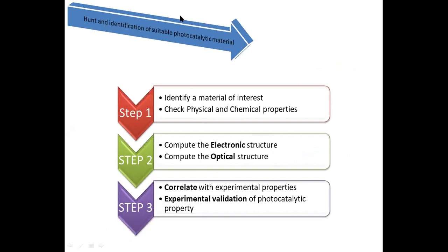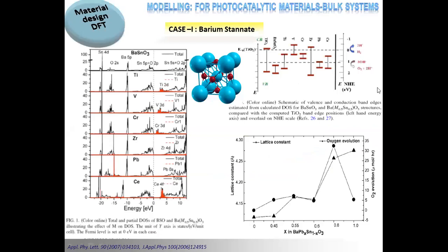So this is the study I am trying to show here, and this slide quickly tells you that barium stannate, BaSnO3, is a material which has a large band gap of 3.2 electron volts. Now, our hypothesis and our idea was, if we select this kind of material and then go on doping, say different dopants like titanium at the Sn site, or vanadium, or chromium, or zirconium, or lead, then how the optical property and electronic band structure are affected, and how that can be exploited for designing a photocatalyst.